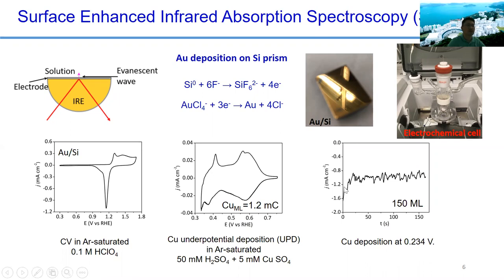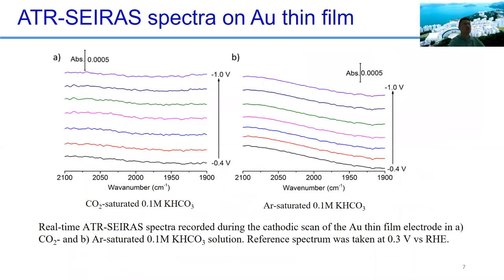And then we can measure the current, basically the charge passing through the deposition. We can control the thickness of the copper. In this case, it's about a 150 monolayers, so it's about 20 nanometers of copper on gold thin film. Yeah, so this is a chemical cell that we developed for this kind of investigation. Okay, so first we want to see whether this gold has any impact on our measurement.